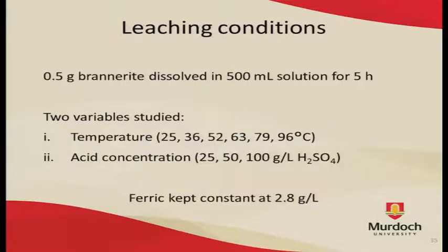In the first series of experiments, the ones I'm presenting on today, I studied the effect of sulfuric acid concentration and temperature. There have been a few papers on the rate at which uranium is released from brannerite and brannerite-containing ore, but not that much on the behaviour of titanium, which I suspect may also be of importance. It's also necessary to study brannerite dissolution in isolation from gangue as well. There are many ways in which the gangue mineralogy can influence the dissolution of uranium that might hide the effect of whatever conditions you're adjusting.